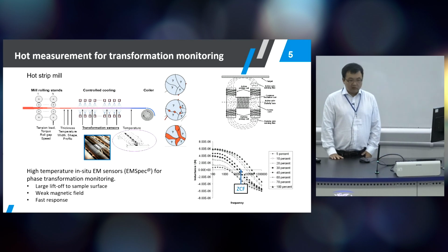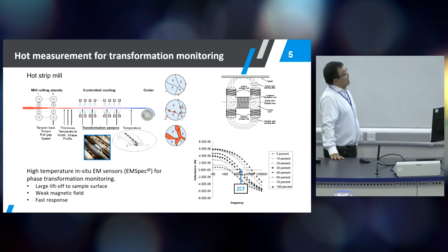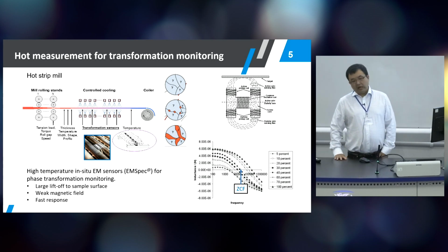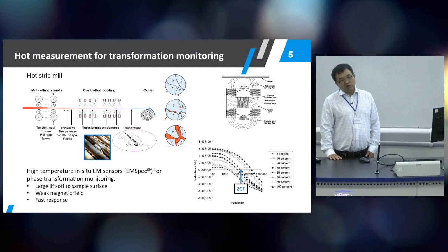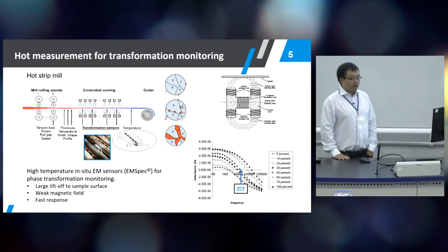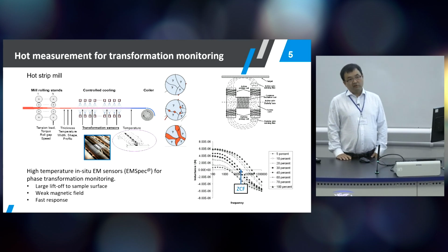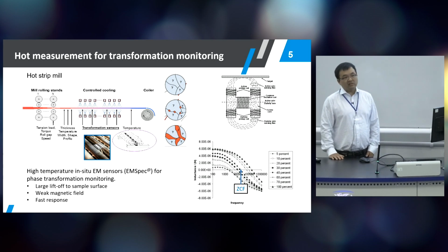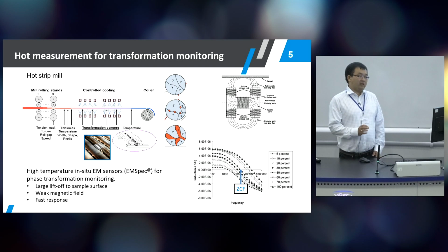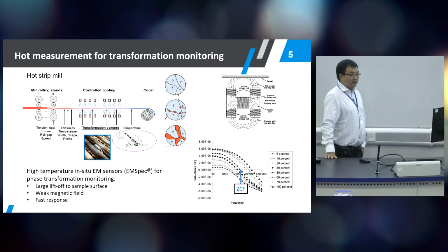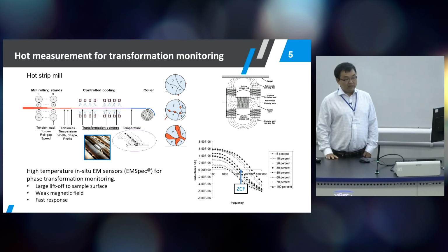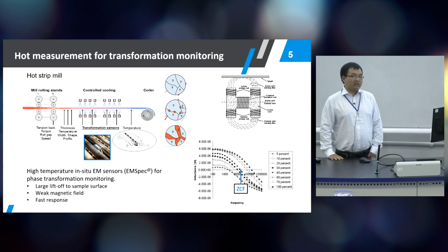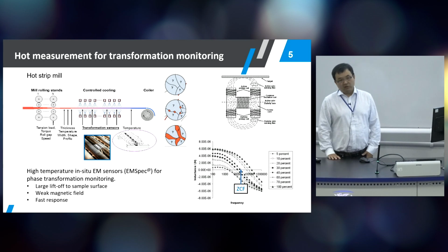What we have researched at WMG Warwick is the online in situ sensor at high temperature. So here we're talking about a temperature range somewhere between 800 down to maybe 400-500 degrees, which is where the structural steel transformation normally happens. So there we face the application challenge of the electromagnetic sensor, that we can't place the sensor too close to the steel sample because of the high temperature. And the other difficulty is that the steel strip or other shape of product will move on a continuous line, and that will introduce more noise to the sensor signal.